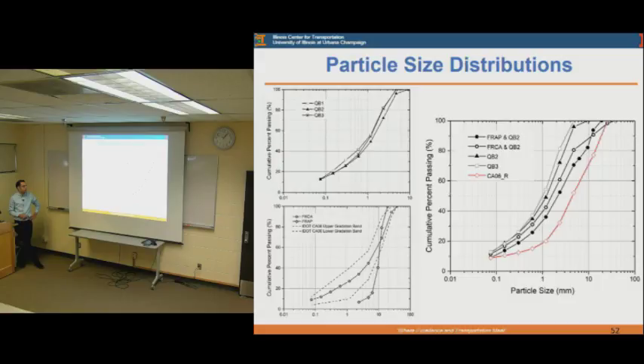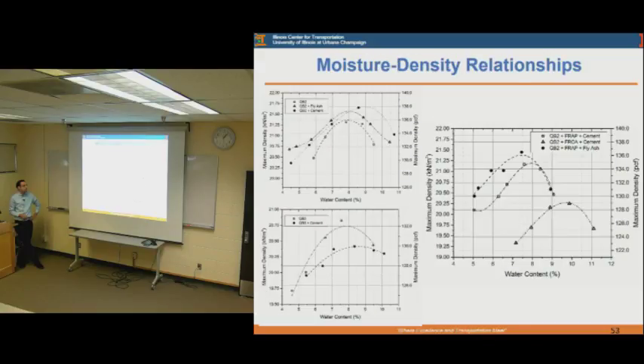Similar to the first presentation, the particle size distribution in the lab was investigated for all the different materials, and then the combination of the materials shown here on the right. These are the combination of materials that were used to construct the test sections. And then also the moisture density relationships, which was also critical this time for the hydration of the cement and the fly ash, as well as to compact all the layers at the optimum moisture content and get the highest possible relative compaction for these test sections.